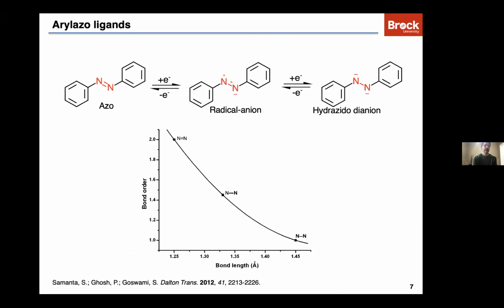So what kind of redox-active ligand platform do we use? We've been looking at aryl azo ligands. Of course, these are well-known ligands that are, again, redox-active. You can take an aryl azo, reduce it by 1 electron to a radical anion. And again, another reduction produces the hydrazido dianion. Of course, you can track what oxidation state you have for your ligand by looking at the NN bond distance. So the bond gets longer as it's reduced.